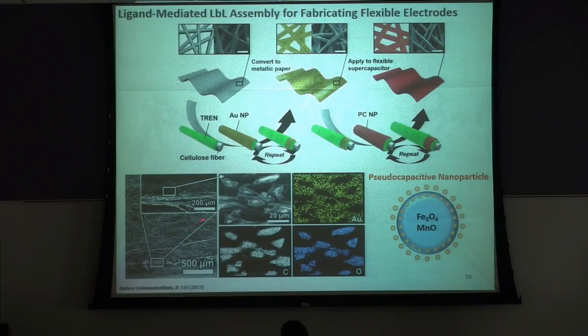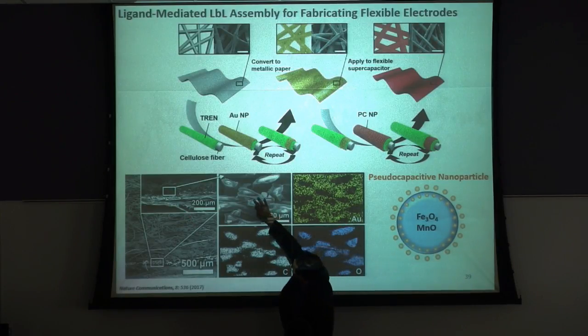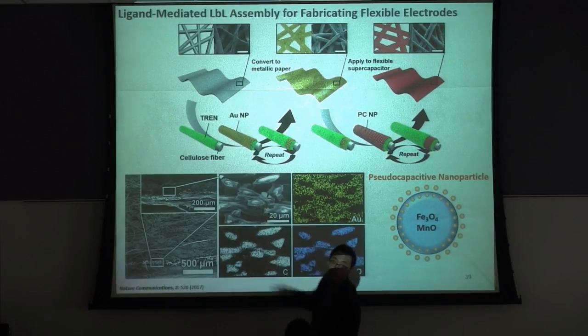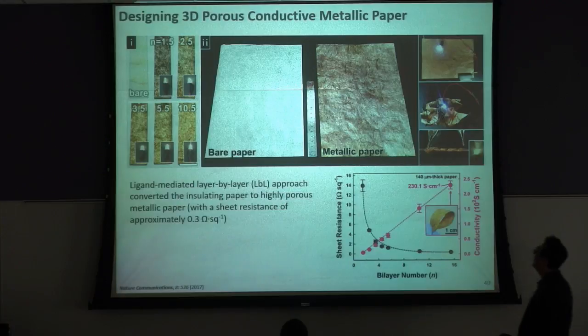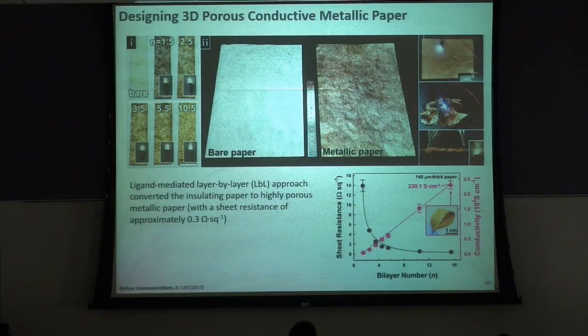We can see the many filaments of the paper. Then we can see the conformal coating of the gold nanoparticle layer around the fabric and also paper. And this is a bare paper. So after repeating this ligand-mediated layer by layer self-assembly, we can convert bare paper to metallic paper. If we look at electrical conductivity, after 16 bilayer deposition, the electrical conductivity is pretty high, more than 230 Siemens per centimeter. So I believe this is the highest electrical conductivity ever reported for this kind of flexible substrate.